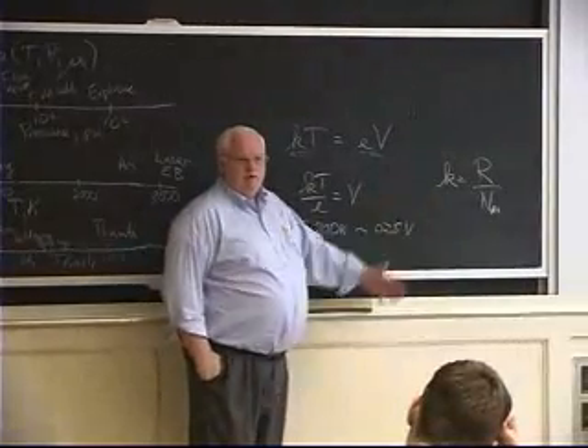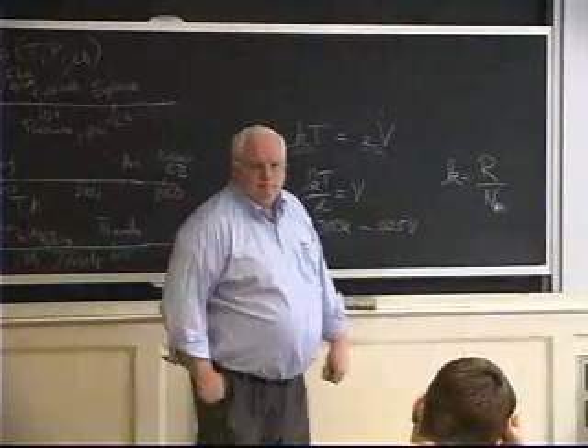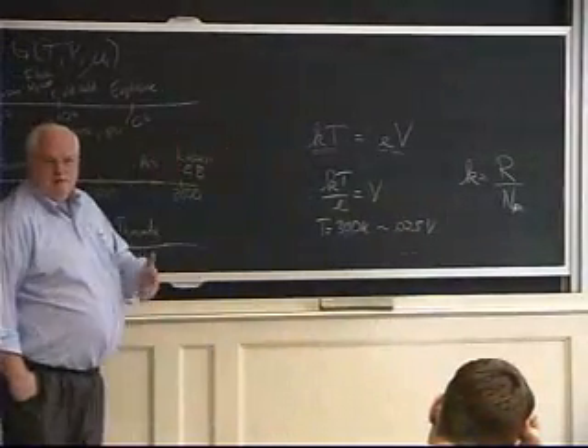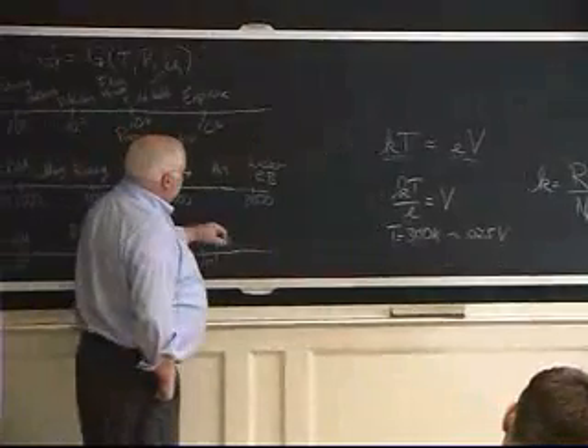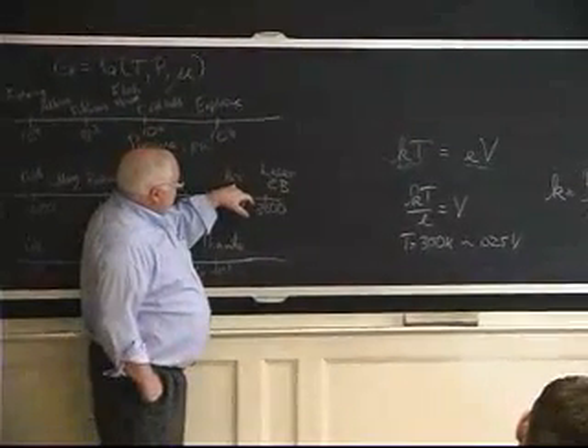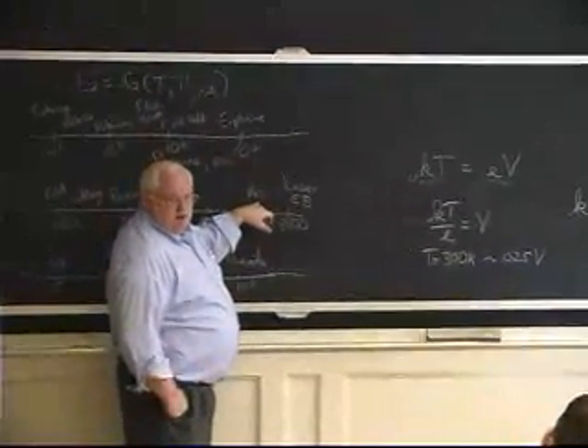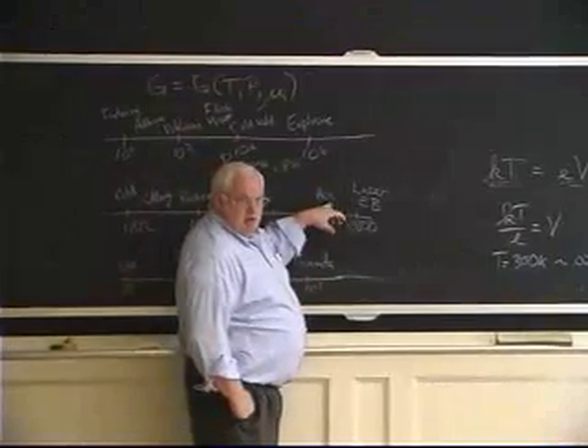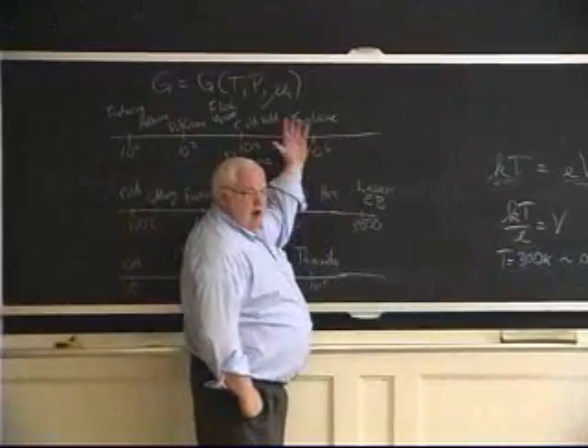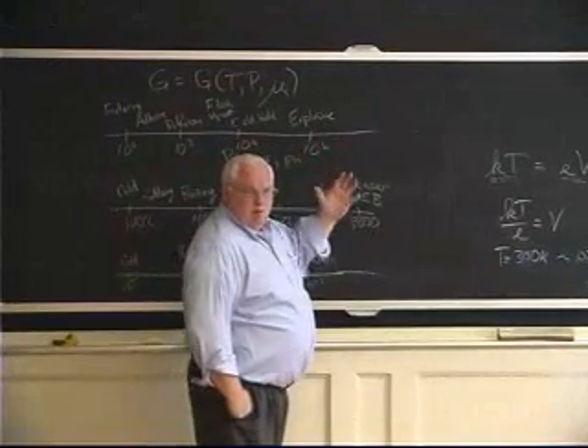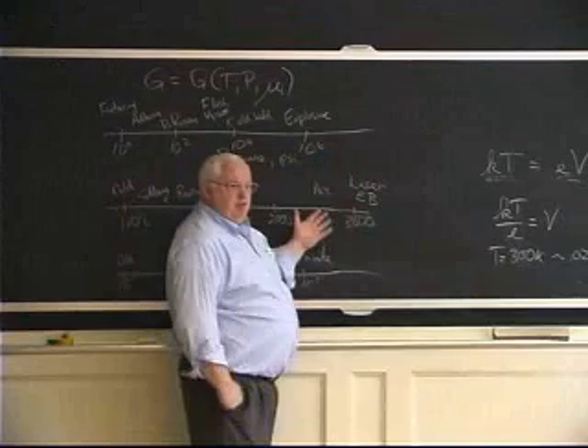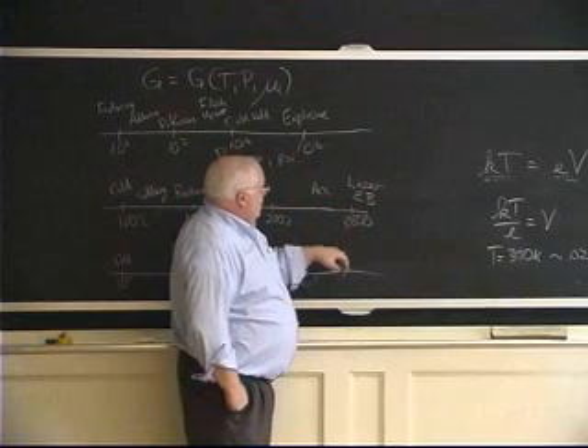I just proved that most things will melt at less than 12,000 degrees. That may not be that useful, but we can actually measure melting temperatures. Nonetheless, arcs will be a sufficient temperature. They can actually break bonds, and we know they do break bonds. Carbon dioxide in arcs breaks down to carbon monoxide and oxygen. Hydrogen breaks down into atomic hydrogen.